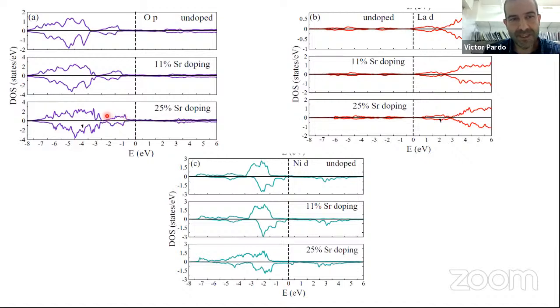So this means that when you dope these nickelates, when you dope lanthanum nickel O2 or neodymium nickel O2 with strontium, their electronic structure is more similar to that of the cuprates. The charge transfer energy gets reduced, and the system resembles the cuprates more.